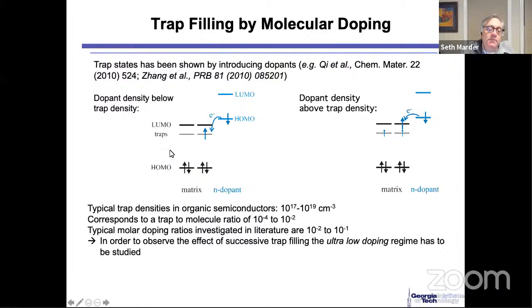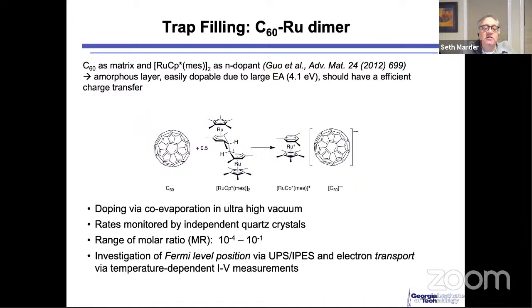the conductivity. Now, if you imagine that these trap states are distributed over a broad energy landscape, but there were very few of them, then as you added a bit of dopant and rapidly filled them, you would begin to see a rapid change in the Fermi energy level as it moves up towards the transport level, the LUMO. However, once you get into the regime of filling these levels, which are there at a bulk density as opposed to a very low trap density, then it's going to take quite a bit more dopant to appreciably change the Fermi level. So the example that we used is to take C60